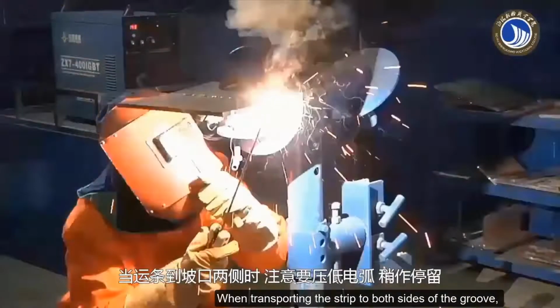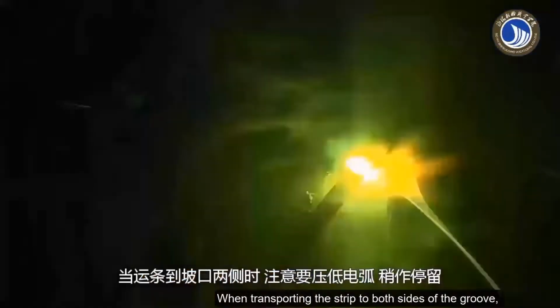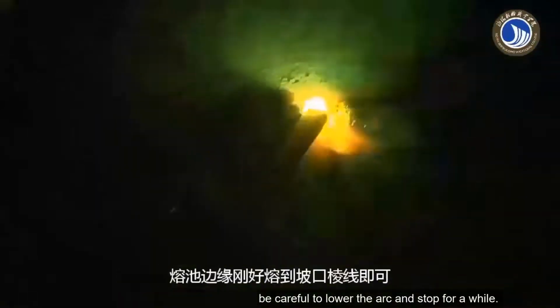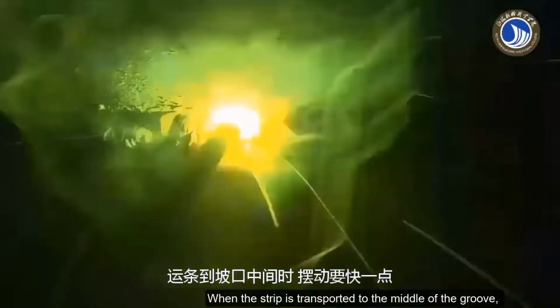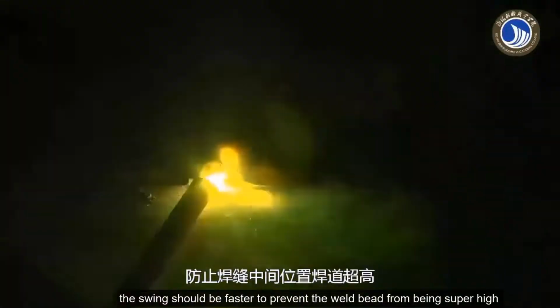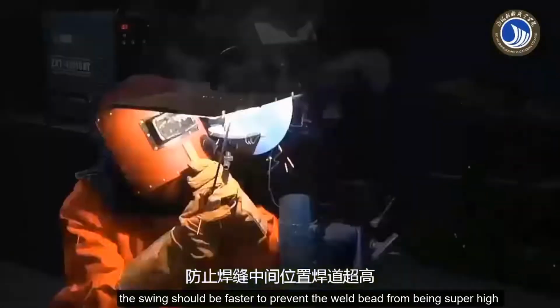When transporting the strip to both sides of the groove, be careful to lower the arc and stop for a while. The edge of the molten pool should just melt to the edge of the groove. When the strip is transported to the middle of the groove, the swing should be faster to prevent the weld bead from being too high in the middle of the weld.